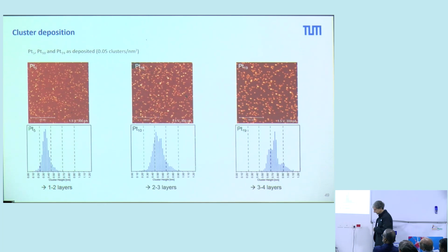And so we were depositing these clusters, platinum 5, platinum 10, platinum 19, on this iron oxide. And you see here height measurements of platinum 5, a rather sharp distribution of heights. It's between 1 and 2 layers. Then we have platinum 10, twice the number of atoms. We are in between 2 and 3 layers. And we have platinum 19, we have 3 to 4 layers. And you see here the size distribution of these clusters, and you see that they are rather identical. That means we are producing these size-selected clusters on surfaces, and we can monitor them by STM images.